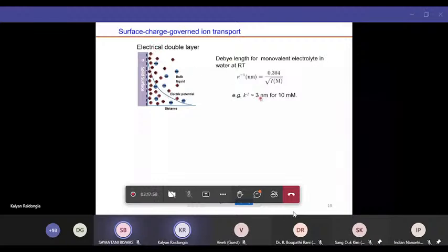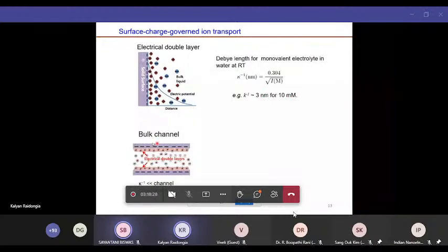Now the interesting thing about the Debye length is that it depends only upon the concentration of the solution. So this is the equation by which the Debye length can be derived. For example, under standard conditions, it is 0.304 divided by the root of the concentration. For a 10 millimolar solution, the Debye length is around 3 nanometers. Now, whenever we make a bulk channel or any pipe, we always have this Debye length. But the size of the pipe is so big that this small Debye length becomes insignificant. So we don't see a very significant effect because of it.